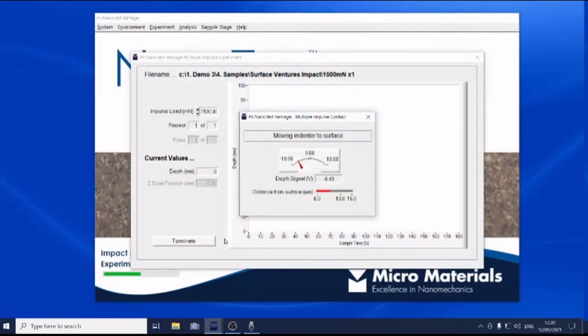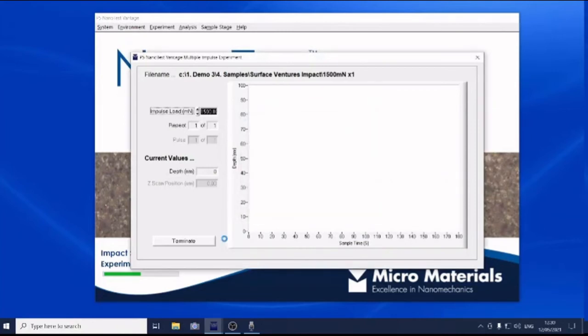Okay, so the instrument is now just placing the indenter on the sample surface to take a reference of where the 0 point is, where the actual starting surface is of the sample. Now it's setting the requested load. So what it's doing is applying this 1.5 newtons of load that we specified. So the probes in contact are just ramping up to 1.5. Okay, and here we go. The impact tests begin. So impact 1, impact 2,